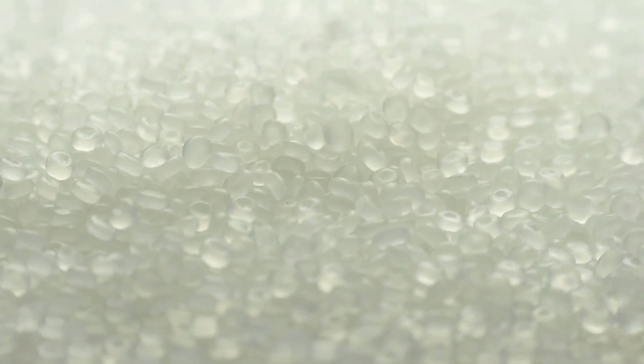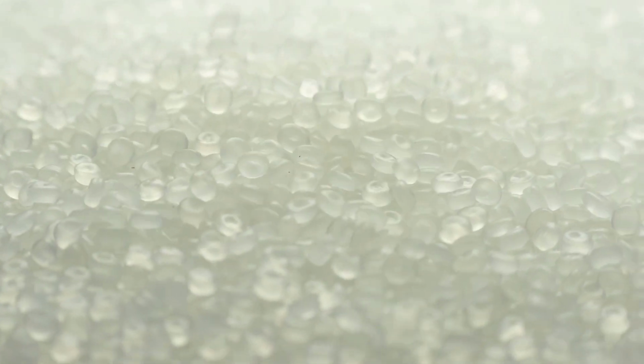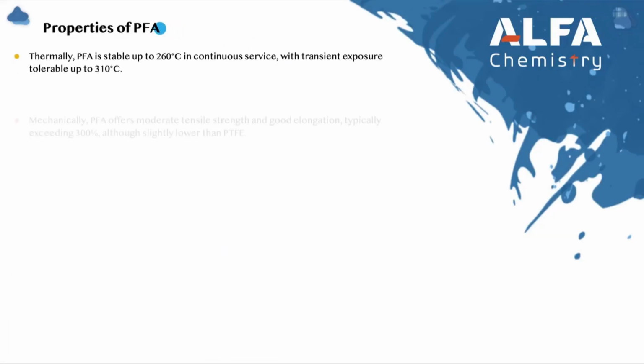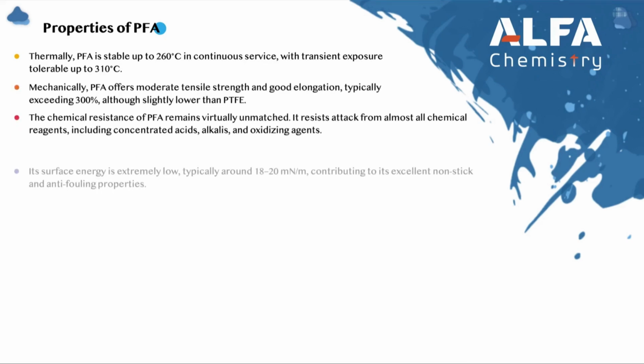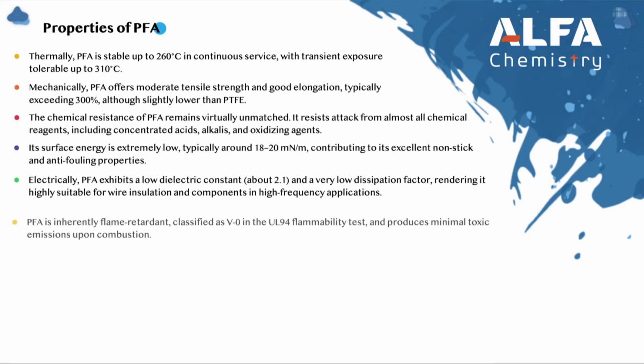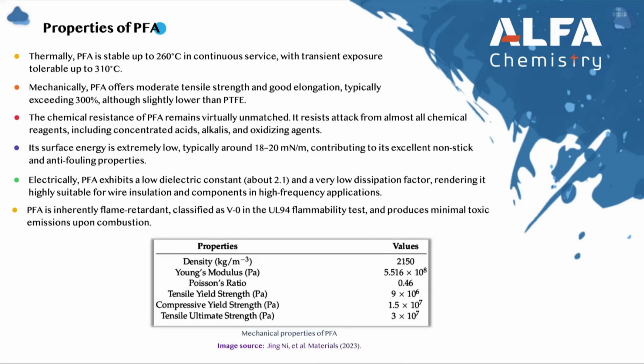Perfluoroalkoxy Alkane exhibits an impressive array of physicochemical properties that place it among the most robust materials known in polymer science. Thermally, PFA is stable up to 260 degrees Celsius in continuous service, with transient exposure tolerable up to 310 degrees Celsius. Its decomposition initiates only at elevated temperatures exceeding 400 degrees Celsius, yielding volatile fluorocarbons and HF. Mechanically, PFA offers moderate tensile strength and good elongation, typically exceeding 300%, although slightly lower than PTFE. What distinguishes PFA is its processability via standard melt extrusion or injection molding techniques, allowing it to be formed into complex geometries, something PTFE fails to accommodate due to its high crystalline nature and gel-like processing behavior.